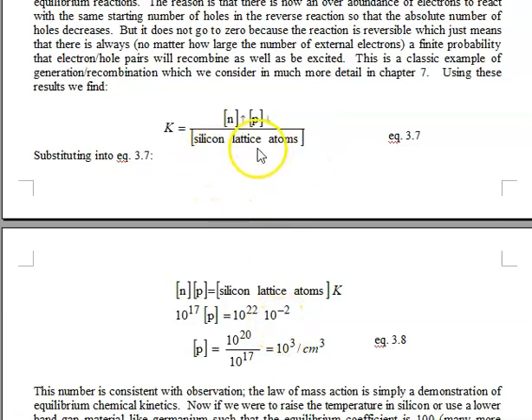The silicon lattice number of atoms is 10 to the 22. So what we find is that the concentration of holes is 10 to the 22 times 10 to the minus 2, which is 10 to the 20th, divided by the new N, which is 10 to the 17th, due to phosphorus doping of 10 to the 17th phosphorus atoms per cubic centimeter, and every one of those is ionized. We find that in this case the number of thermally generated, and I emphasize the fact, thermally generated holes goes down to 10 to the third. It was 10 to the 10th, it goes down by 10 to the 7th to 10 to the third.